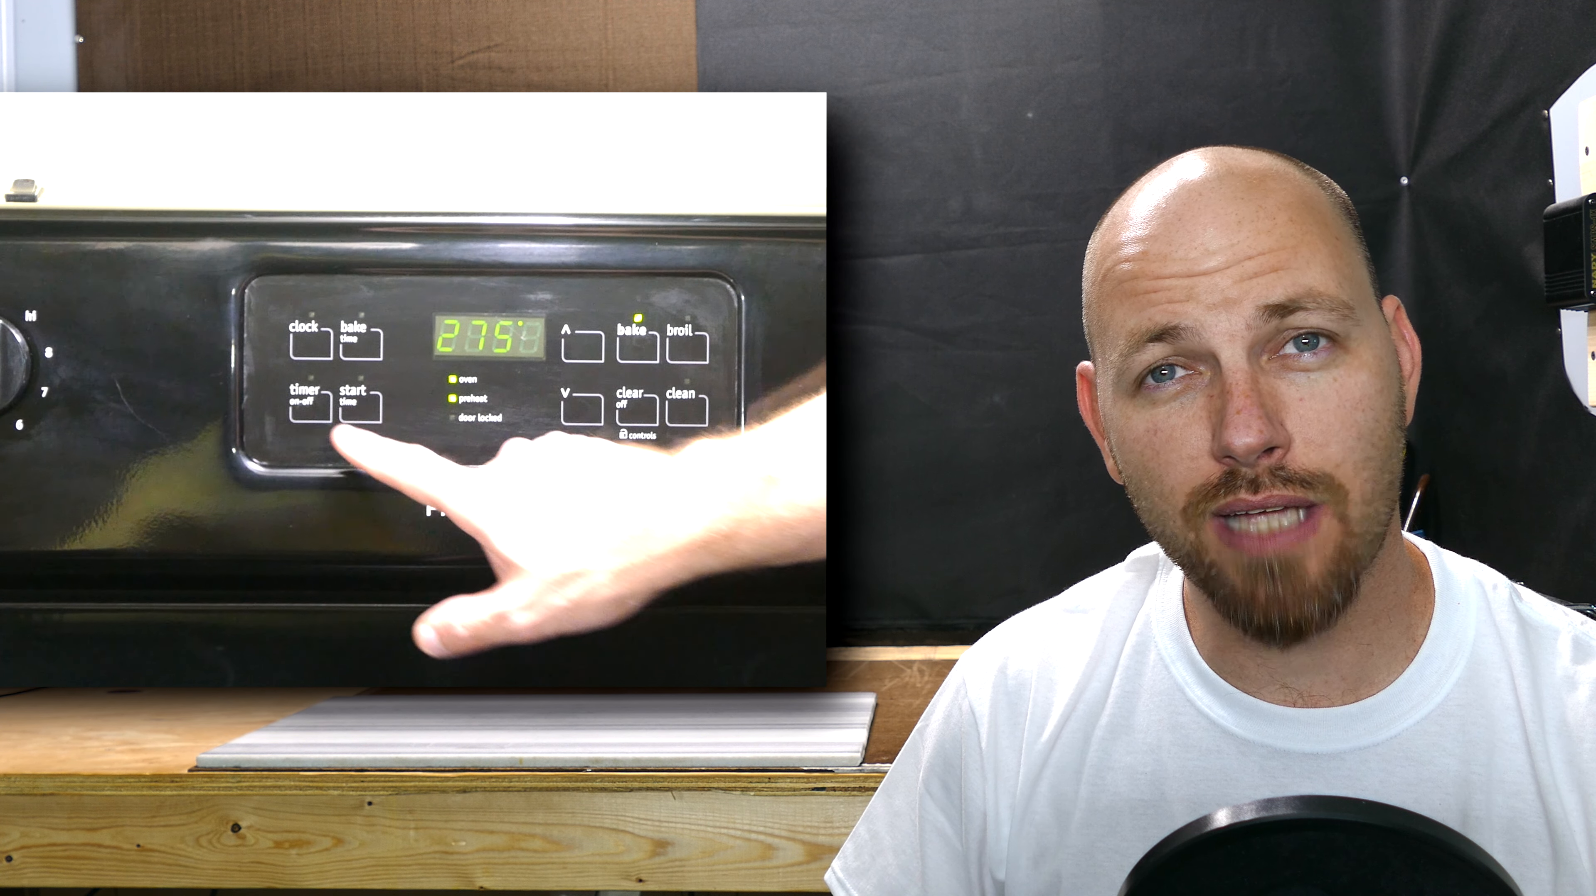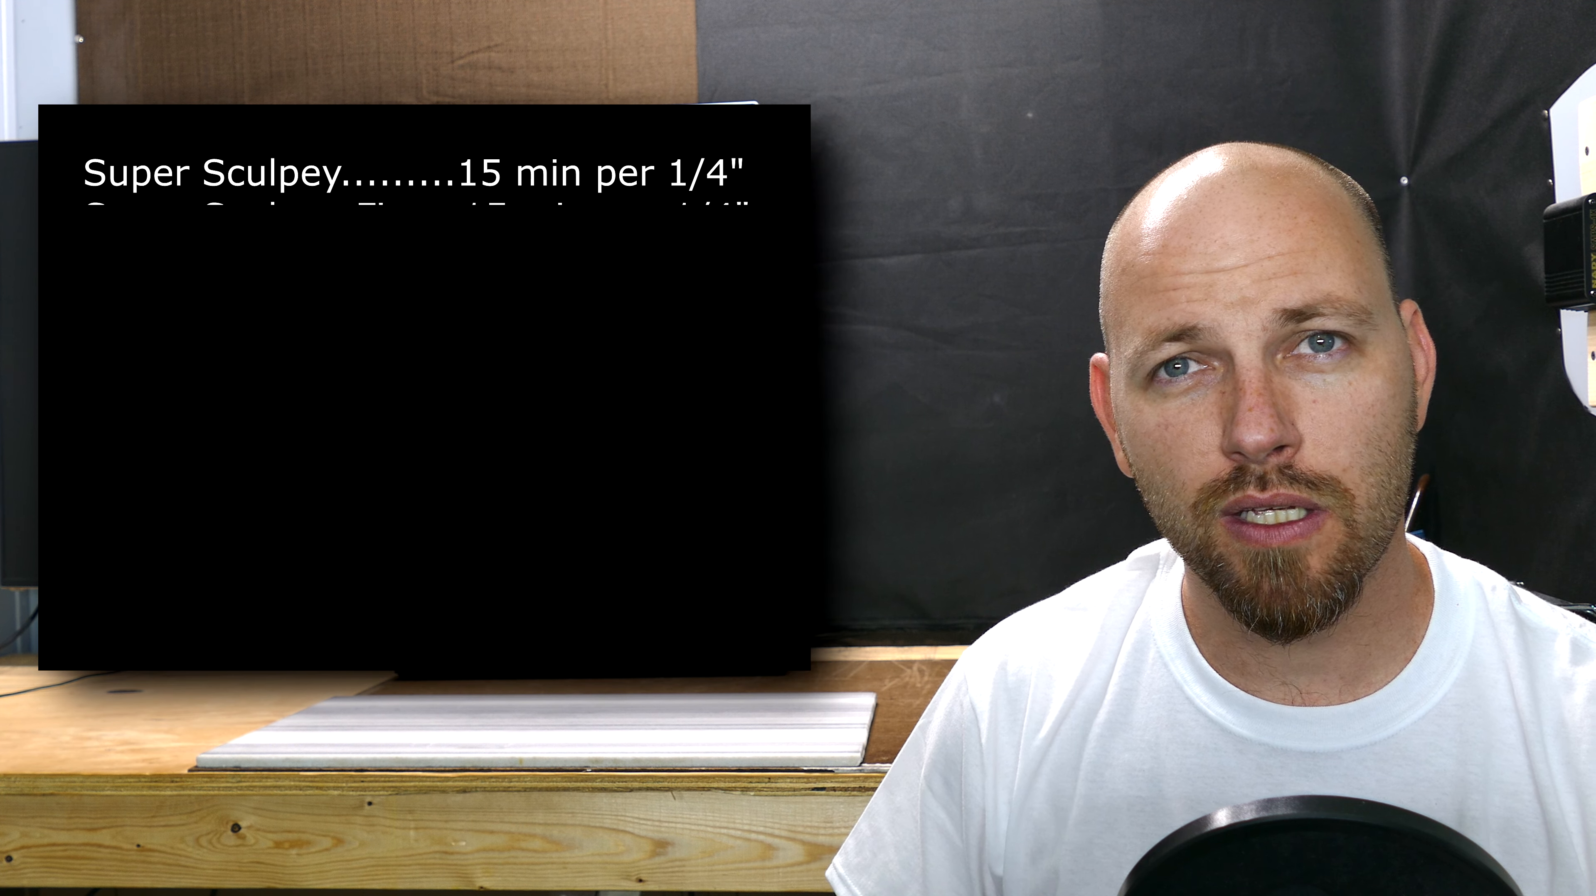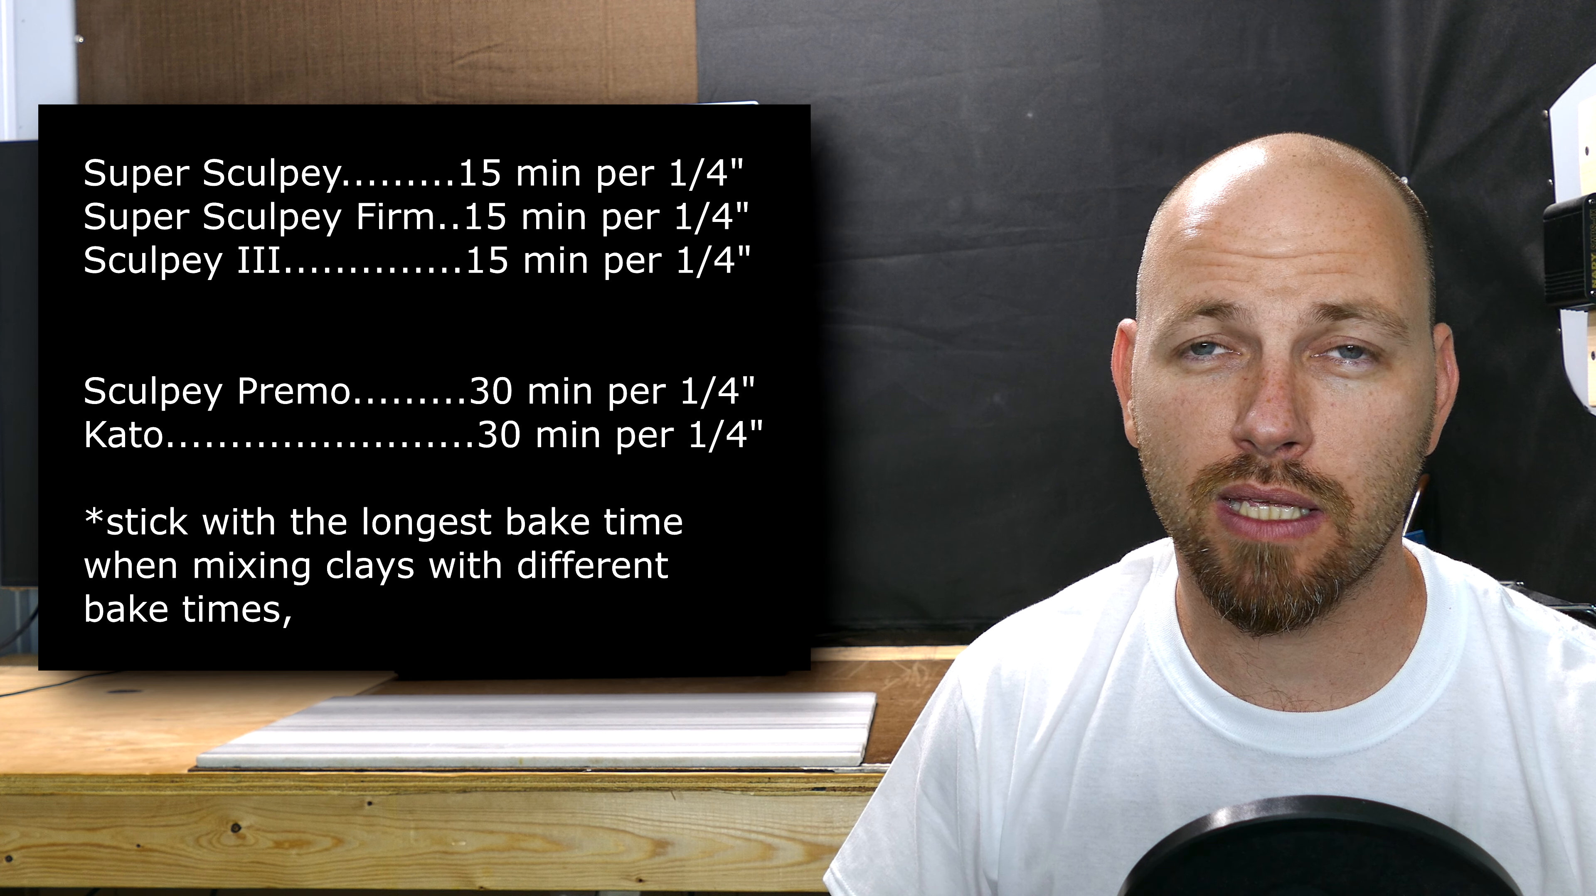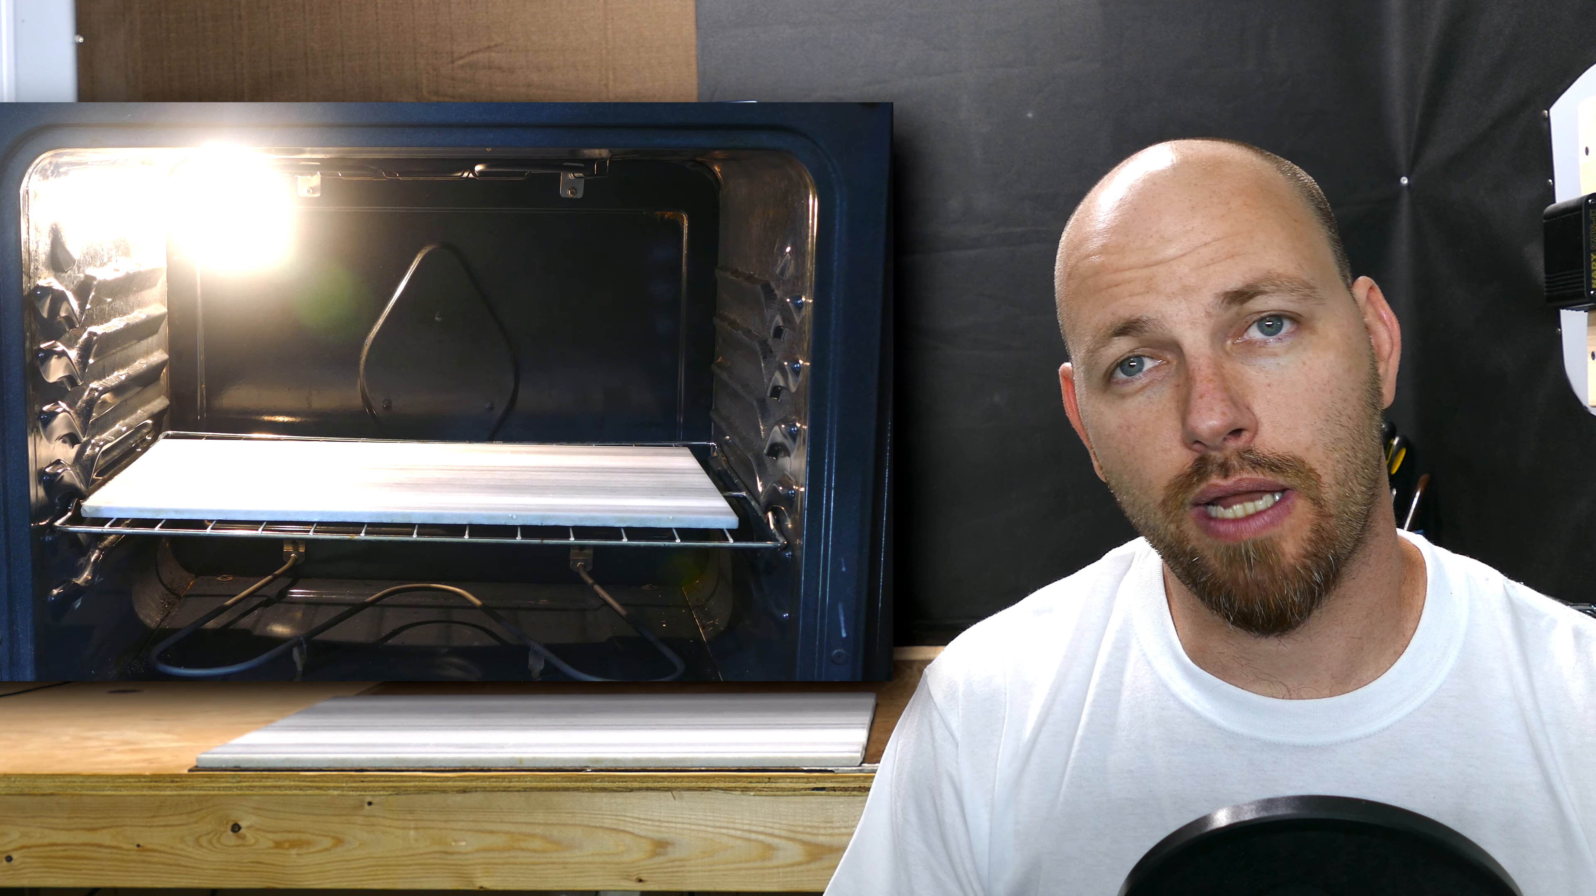Next, bake for the length of time the clay specifies for, and in this case it's 45 minutes. Follow the longest bake time if there's a difference between the two clays when using a mixture of clays. For example, Super Sculpey, Sculpey, Sculpey 3 are all 15 minutes per quarter inch thickness. But Sculpey Premo and Kato are up to 30 minutes per quarter inch thickness. So if you mix one pound of Kato with, I'd say, Sculpey 3, I would stick to the 30 minutes. But if you're mixing Super Sculpey and Super Sculpey Firm, just stick with the 15 minutes since nothing changed.